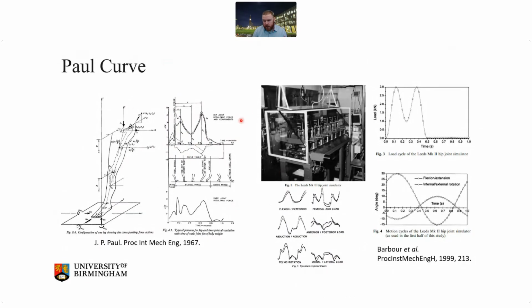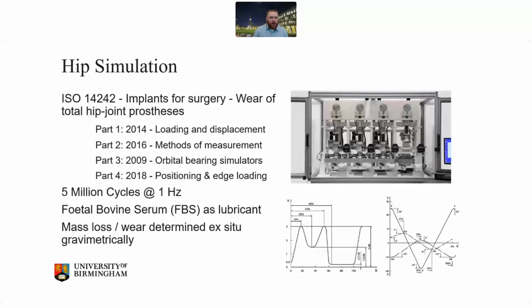So it was this Paul curve that was initially applied on the Dowson simulator, but ultimately this has been simplified, driven by a need to standardize the testing profile, initially into what was referred to as the Leeds Mark II profile, where you had, again, a simplified twin peak profile for heel strike and toe off with a swing phase, and then a collection of sine waves, leading ultimately to the development of the modern standards, where the focus is to standardize the testing methodology in order to determine a benchmark long-term wear rate for a device or for new product introduction. So the ISO 14242 standard concerns hips.